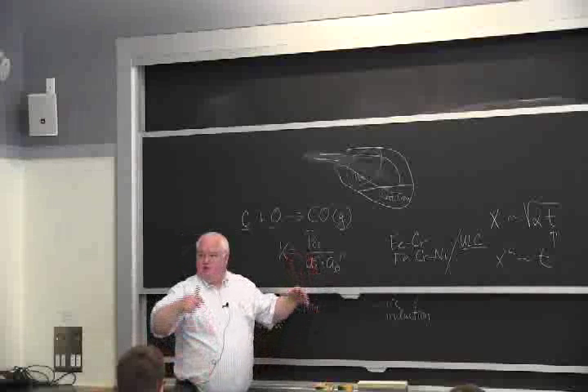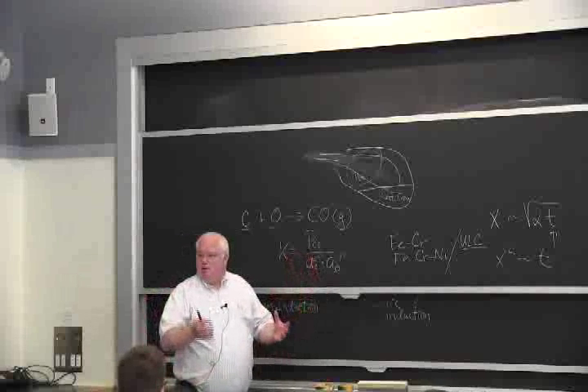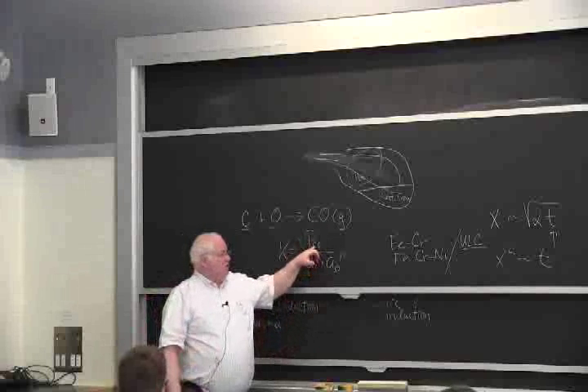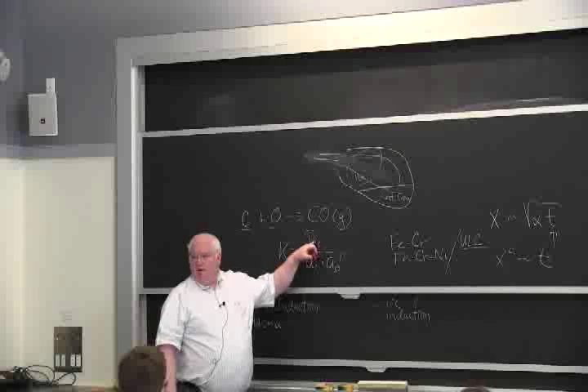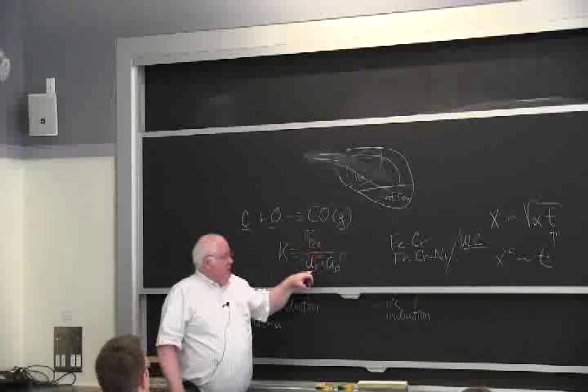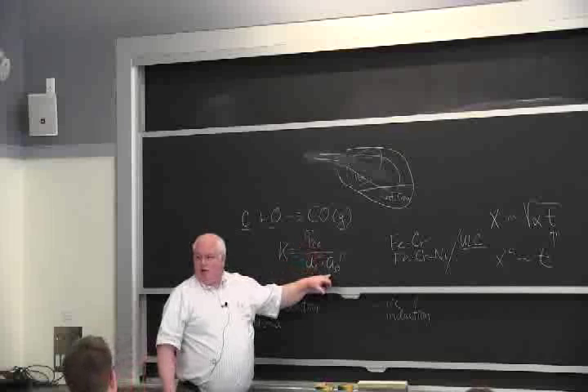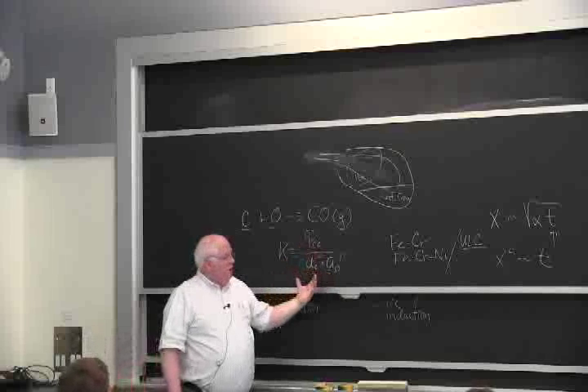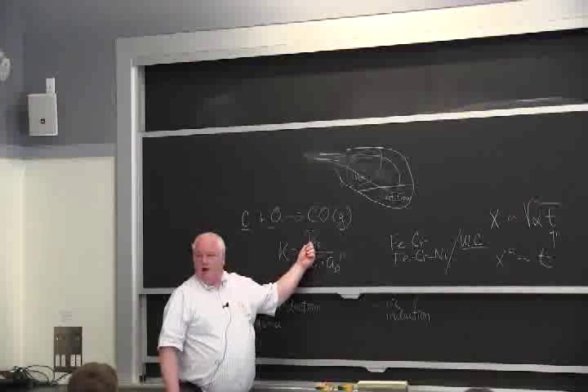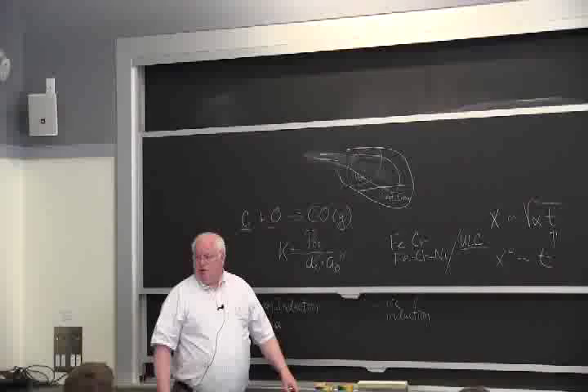Well, if you're just getting a carbon monoxide boil in the steel bath, it's 100% CO, and that's 1 atmosphere. So 1 over the product of these, you can't get the carbon down unless you get your oxygen up. Okay, well, if you drop this by a factor of 100, by having 99% argon and 1% CO, you can get this down much, much lower.